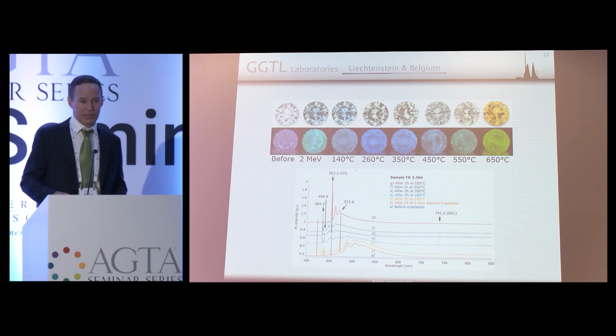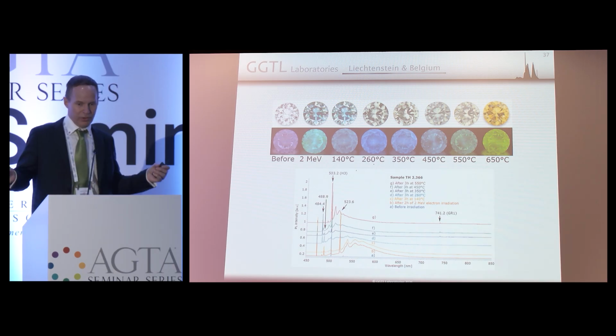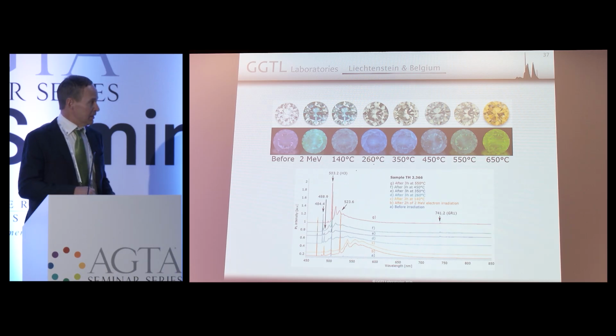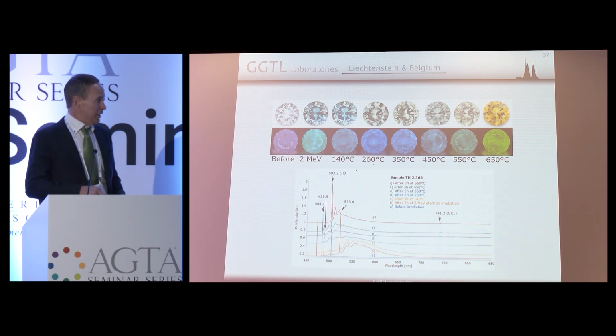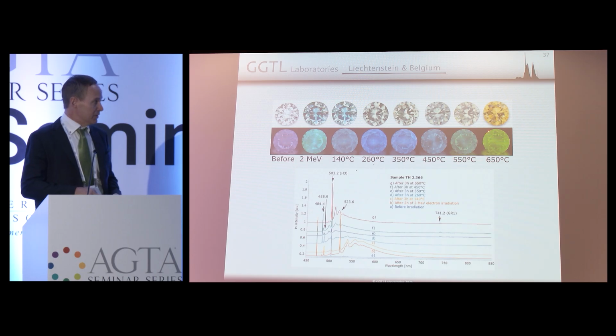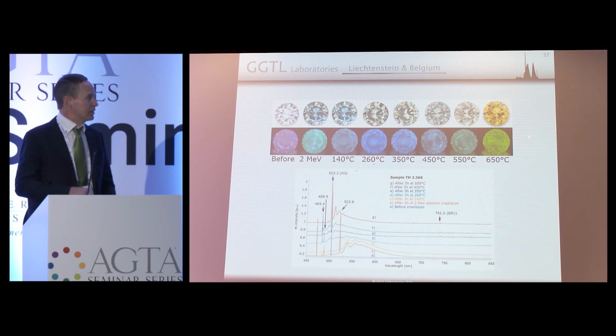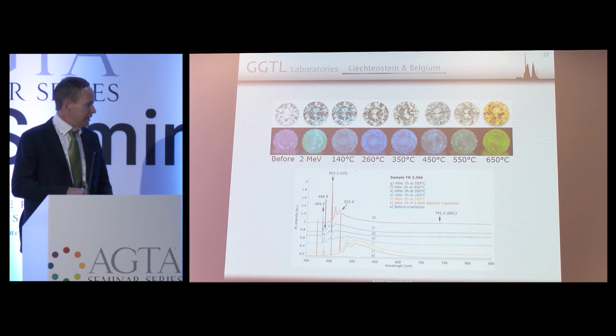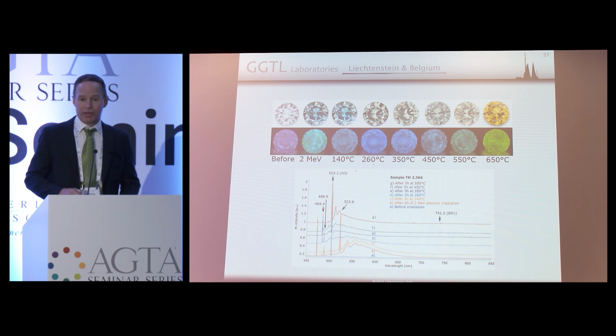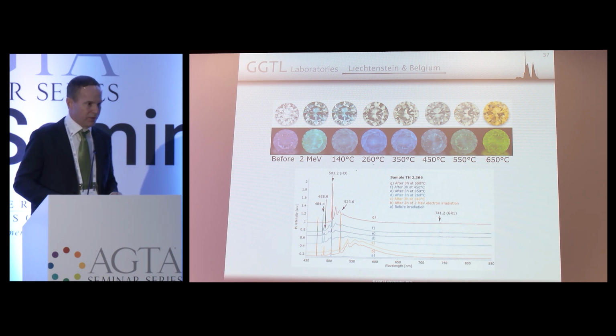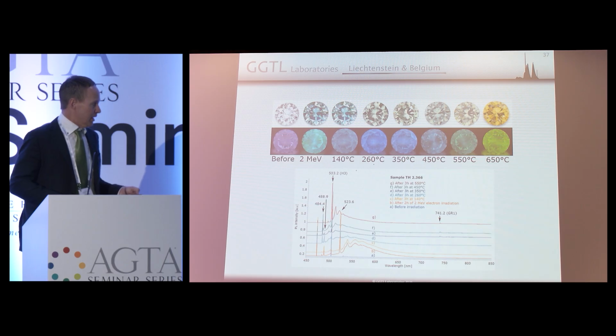That's when the vacancies that you introduce by irradiation start to move all around and catch the nitrogen. Then they form NV centers, such as H3 and H4. And those things give you this yellow color and the green fluorescence. And you can tell it all in every step here. Here you got before irradiation. This is straight after irradiation. So that's this fluorescence. And then at 650, you have a really strong H3 center, which is this green fluorescence here. So this is the sequence of a regular type 1A diamond, Cape type, after irradiation and annealing.